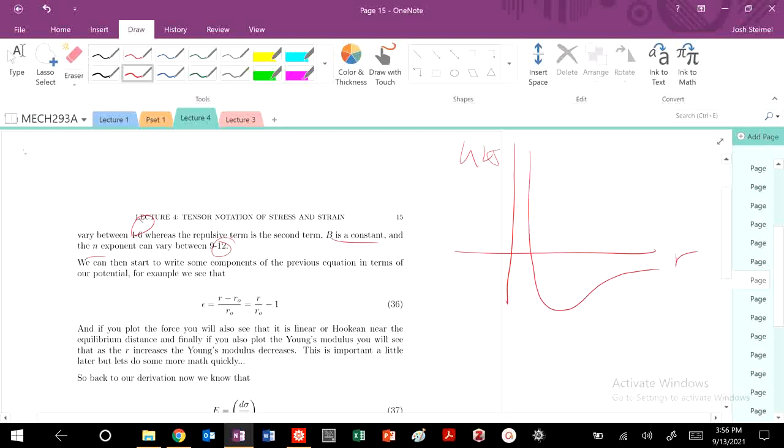strain, because right now I have this expression. So it's 1 over omega, d squared U d epsilon squared. And I know that this is basically the distance between my atoms. So right here, there's that equilibrium distance, and then we're separating them larger. So if I'm stretching my material, I could relate this r distance to my strain. And actually, we could write it here.